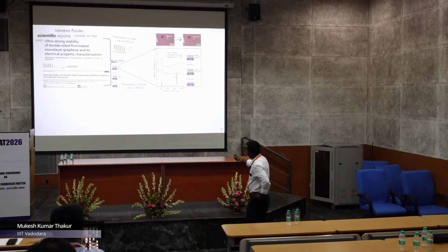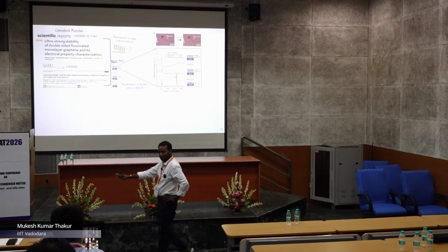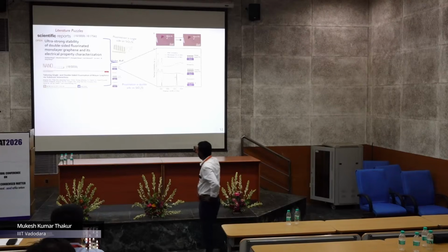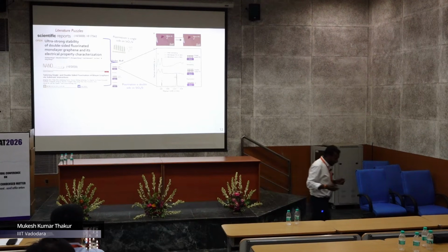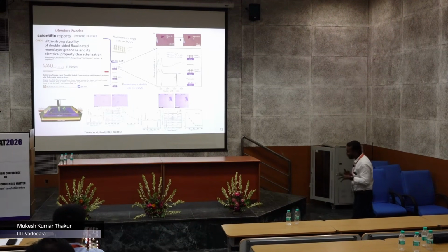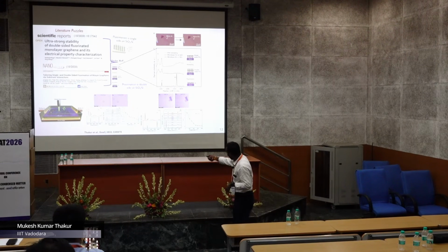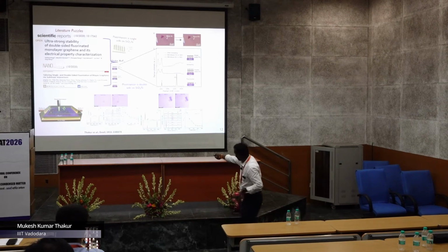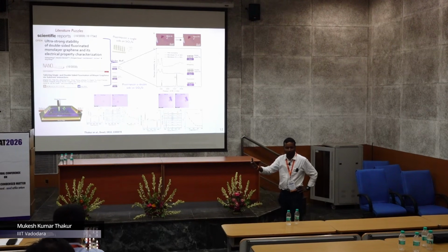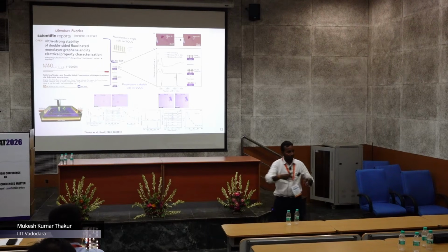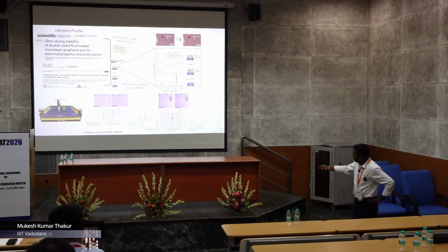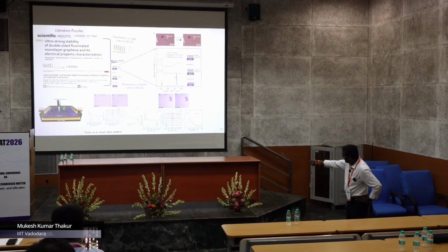So basically when you heat, one side fluorine will go and the second side is still there, and that's why you see clearly this D and G mode. So they are fighting. And what we observed was not true in our case. All the samples were CVD, very high quality, with a very high degree of fluorination in all the cases. Ours was the in situ Raman, with better control than annealing the sample in the furnace. When we increase the temperature, this I_D/I_G is decreasing, and you see clearly this D mode is decreasing. But here they say it's not. This is a CVD sample.